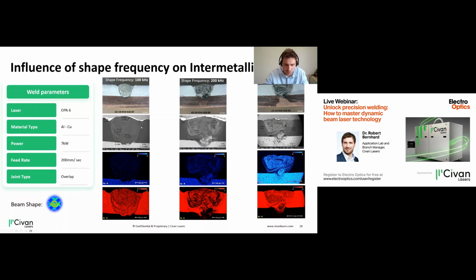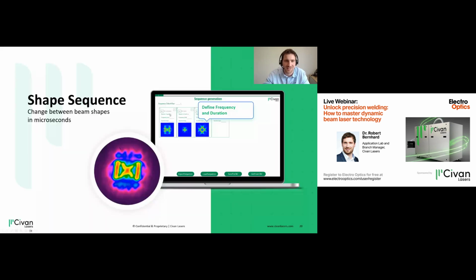So all the process parameters are identical, but the welding results in different dilutions. So when you go from left to right, we can see 100 kilohertz. Just a little copper-based material goes up into the weld, but we can very well increase that on the right side by doing more and more dilution due to the shape frequency. There's more again, I guess.